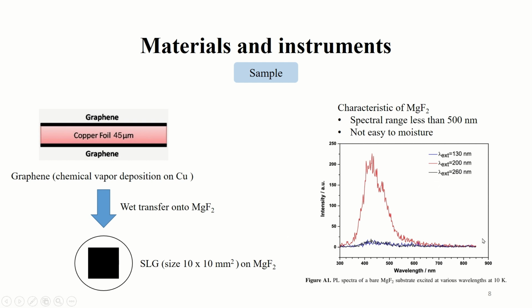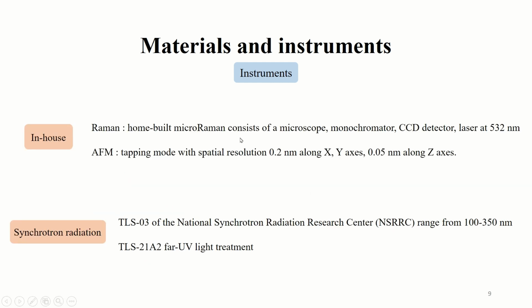This figure A1 is the PL spectra of magnesium fluoride at various wavelengths and 10 Kelvin. Only when the excitation wavelength is 200 nanometers does photoluminescence exist. In-house instruments include Raman and AFM. Raman is a home-built micro-Raman consisting of a microscope, monochromator, CCD detector, and a laser at 532 nanometers. AFM is set to tapping mode with this resolution.